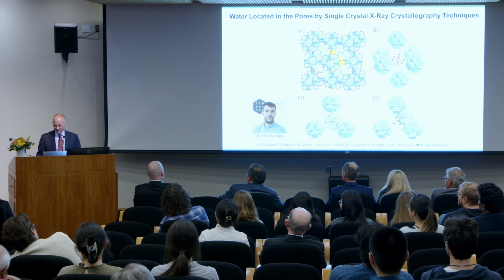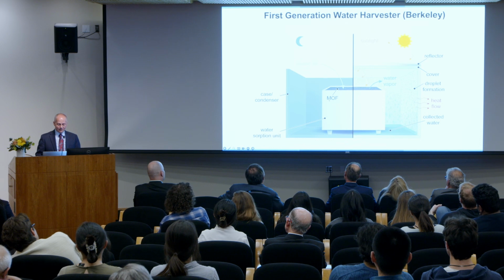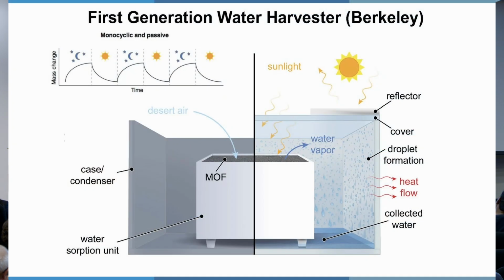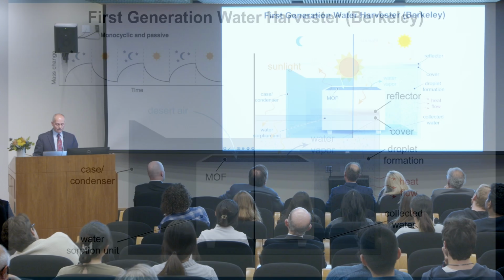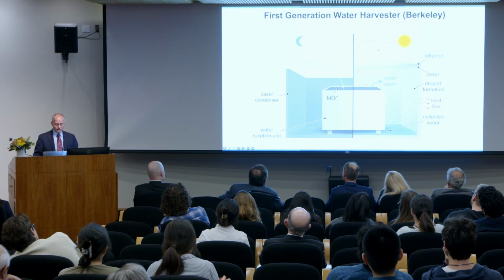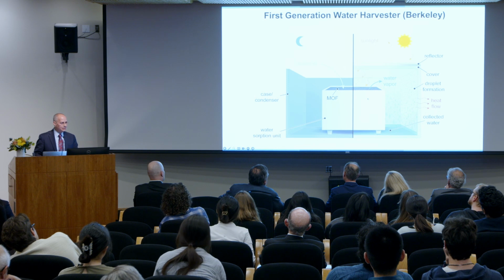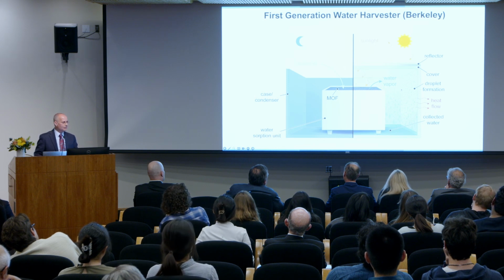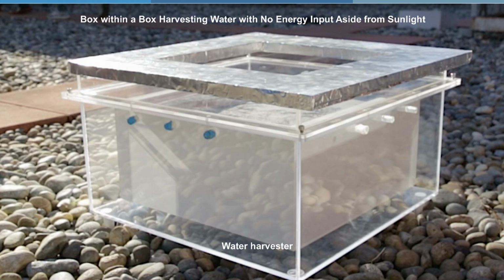And so we went our own way and we built a device that has a box, basically a box of MOF within a larger box. At night, this box contains, in this experiment, 1 kilogram of MOF. The MOF I just showed you, 801. Desert air goes into the MOF. Water is trapped in the pores, as I have been describing. You close the outer box and expose it to sunlight during the day. The inside heats up. Water comes out, condenses on the walls. Now I have drinking water. No energy input aside from ambient sunlight.